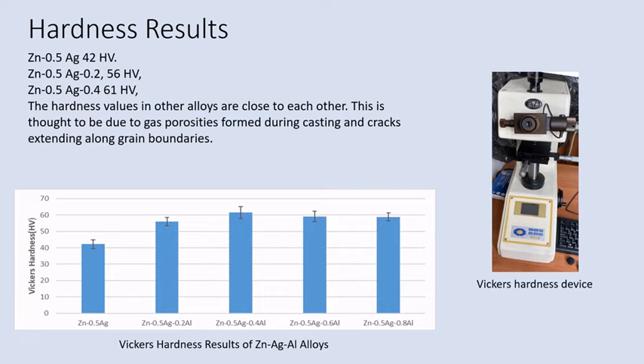And you will see the hardness results here. We used a Vickers hardness device to determine the Vickers hardness values, and from our literature research we know zinc has a hardness of 30 Vickers. When we added 0.5 silver, the new value is 42 Vickers, and after we added aluminium, it increases until the point of 0.4 aluminium. After that, it stops, which is thought to be due to gas porosities formed during casting and cracks extending along grain boundaries.